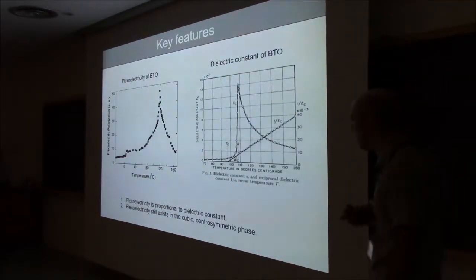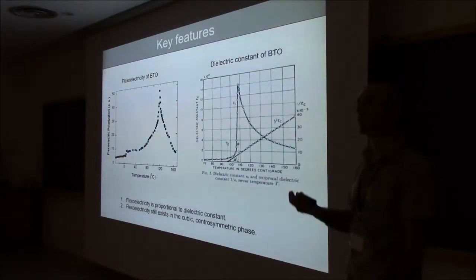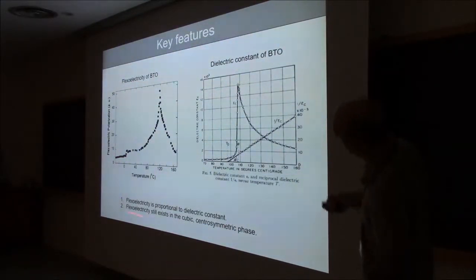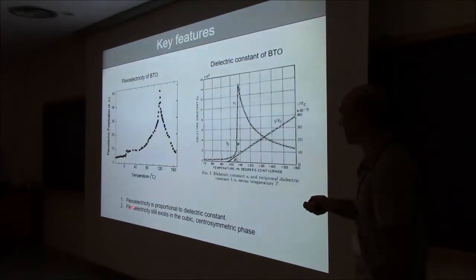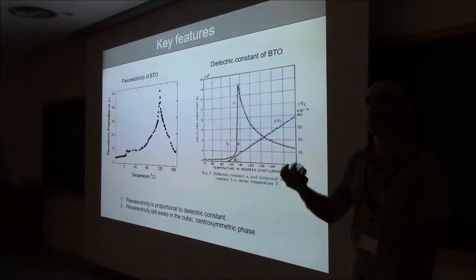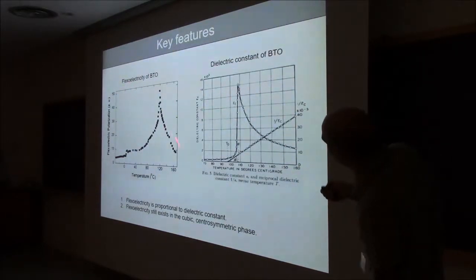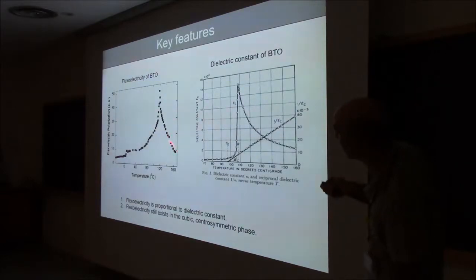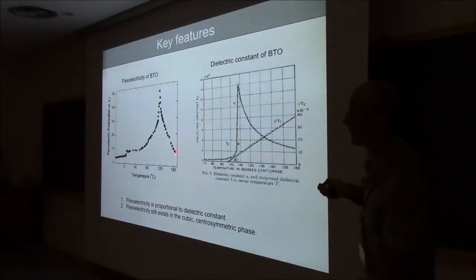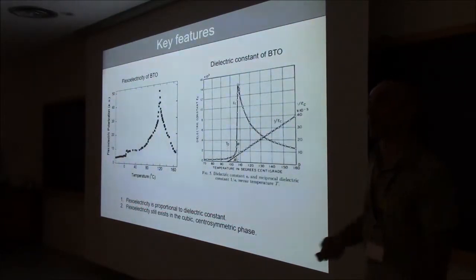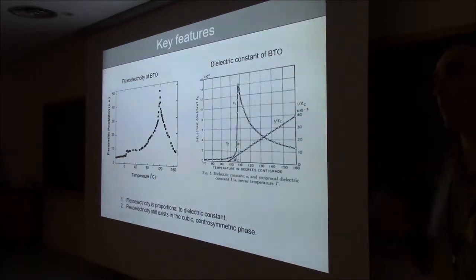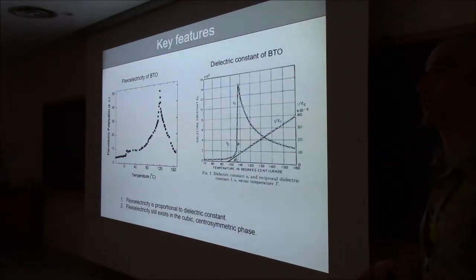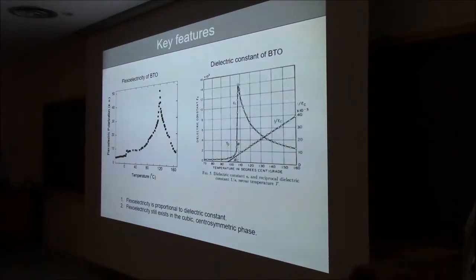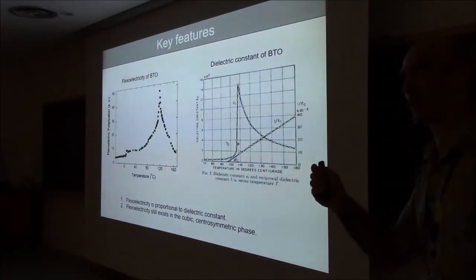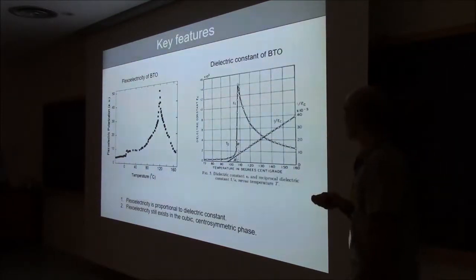So that brings me to the second important feature of flexoelectricity. The first, of course, is that it's possible even in centrosymmetric materials. In the case of BTO, you see that it still exists in the paraelectric cubic phase. So here, BTO is cubic and paraelectric, but it's still flexoelectric. Point two, it's proportional to the dielectric constant. And because it is proportional to the dielectric constant, flexoelectricity would be most important in ferroelectric materials. Everything can be flexoelectric, but ferroelectrics are more flexoelectric, like Animal Farm.